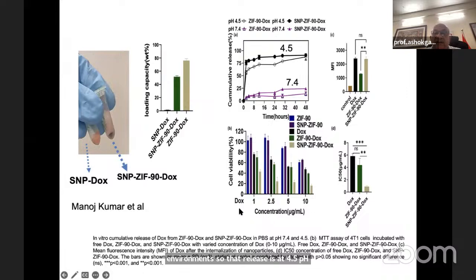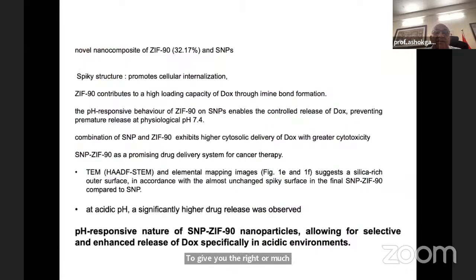And then you can study the cell viability. So you can see the silica nanoparticle ZIF90 DOX gives the least cell viability. Also, the IC50 studies show that the silica nanoparticle ZIF90 DOX needs much less IC50 compared to pure doxorubicin, which is a drug for anti-cancers, or ZIF90. So you need the silica nanoparticle and ZIF90 along with the DOX to give you much more efficient behavior. Right. So this nanocomposite, what does it do?